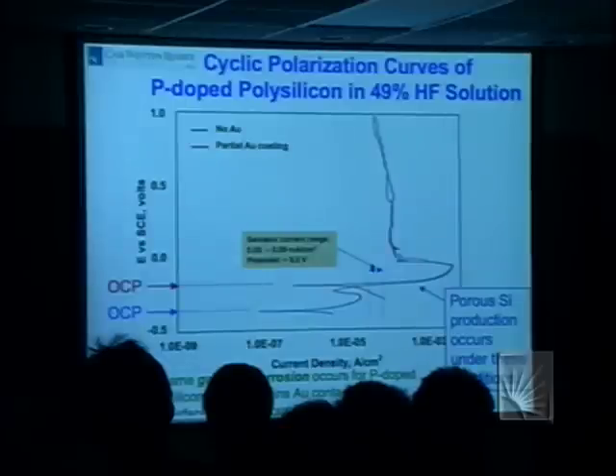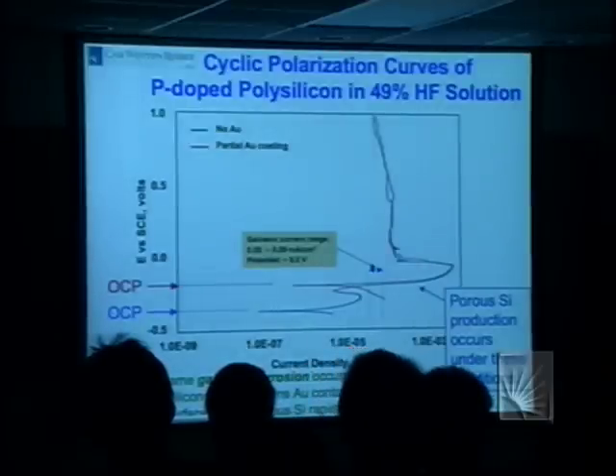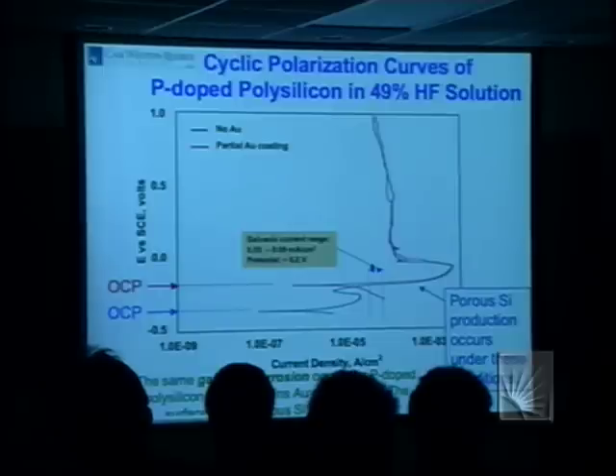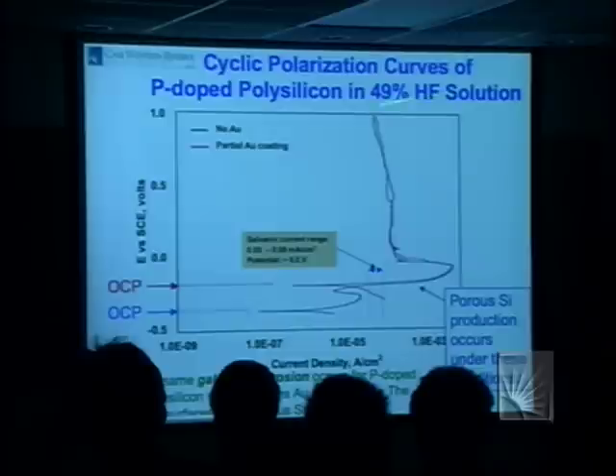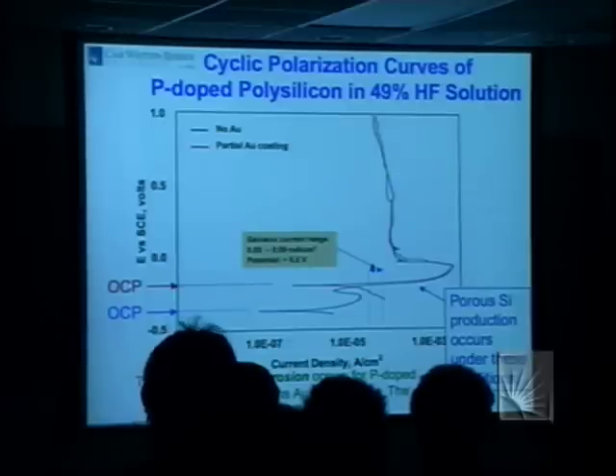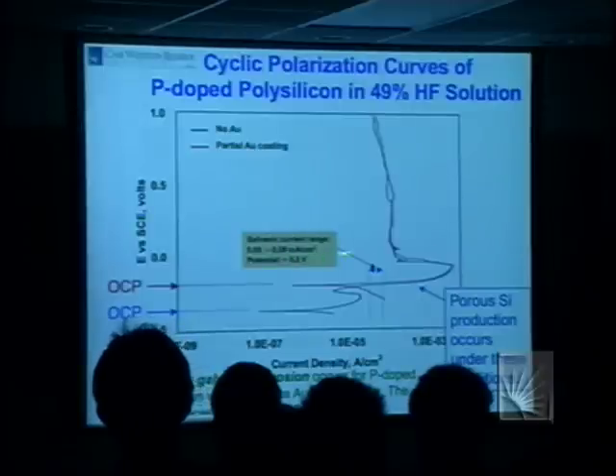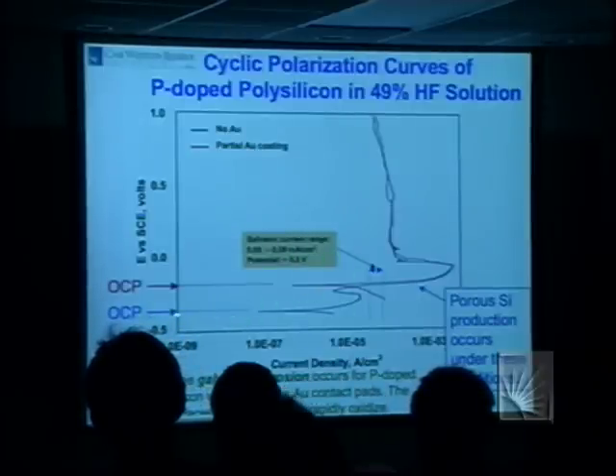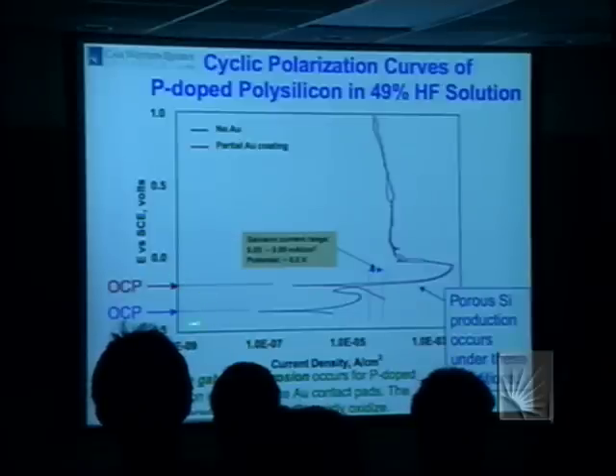And the origin of this can be seen in what are called cyclic polarization curves. If you're not an electrochemist or a corrosion engineer, you might not be familiar with these, but all this is, you apply a potential and measure the current flow, and you can learn a good deal about the electrochemical dissolution of materials by the particular form of the cyclic polarization curve. The important point about this slide is that when you have pure silicon, that's the value of its open circuit potential. But when you have gold on silicon, it becomes more cathodic by about 200 millivolts. And that results in this kind of current flow.